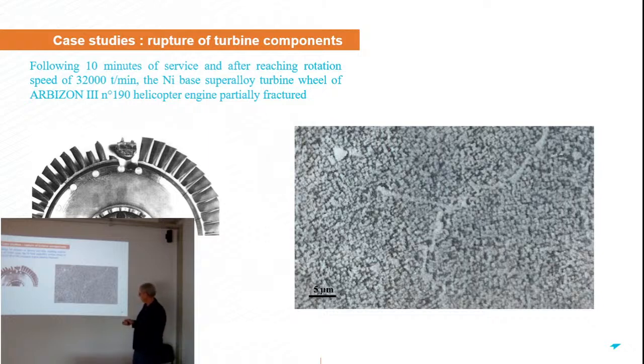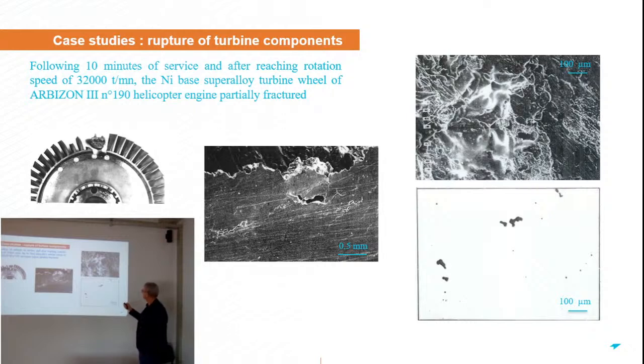If you go more deeply in the analysis, you can see here a quite nice microphotography of the material, and you can see on this micrograph the very typical gamma prime microstructure, a two-phase microstructure, very typical of nickel-based superalloy. So the material, in terms of its microstructure or phase structure, is okay. But if you go more deeply in the analysis, you can find what we call micro porosity. You can get in the microstructure of the material a lot of pores. You can see here. And this is an analysis to evidence the presence of pores here. You can see here the scale. You can see in the material a lot of defects due to the manufacturing.